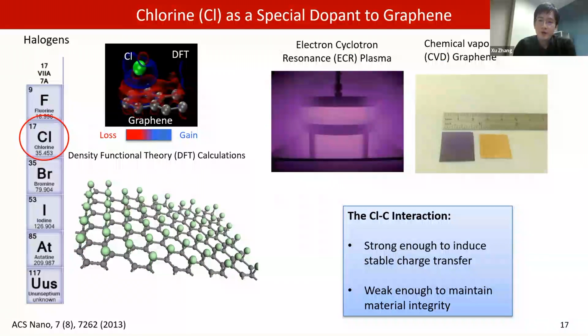Based on DFT calculations, we found that chlorine in the group 7A of periodic table is very promising to introduce strong doping in graphene because of their relatively large electron affinity. At the same time, the underlying graphene can largely maintain its sp2 planar structure. Chlorine can introduce the right amount of interaction with graphene, and that is the key to get non-invasive doping.